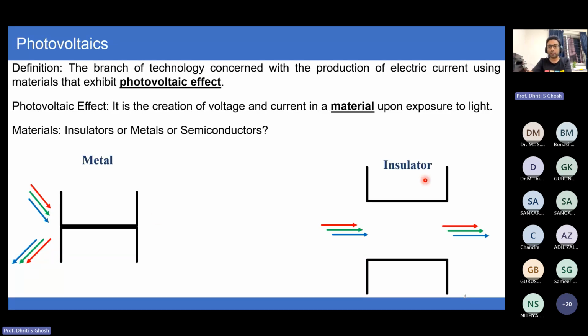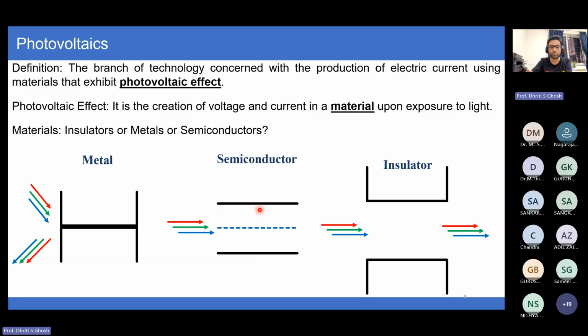What happens in the case of insulators? In an insulator, the conduction band and the valence band are separated by a very large band gap, typically above 3 electron volt. In such cases, even if photons come in, those photons are not absorbed. They come in and pass away, so they are not utilized by the material. However, in the case of semiconductors, the band gaps are typically in the range of 0.7 electron volt to around 2 electron volt, and this band gap syncs with the incoming photons in the visible part of the spectrum. This means if light falls on a semiconductor, the chances of it being absorbed are very high. Metals cannot absorb, insulators cannot absorb, but semiconductors can absorb the incoming light. So we need to use this type of material for making a solar cell.